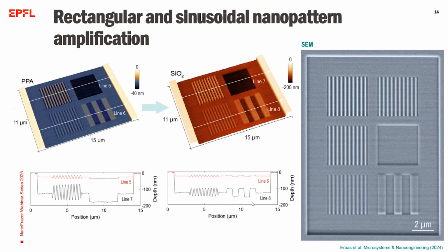With this approach, any arbitrary shape, like both binary and grayscale nanopatterns, specifically rectangle and sinusoidal nanopatterns in our case, change aspect ratio as a result of the plasma etching process. So it's not limited to one specific design. Any arbitrary shapes are able to be amplified during this plasma transfer.